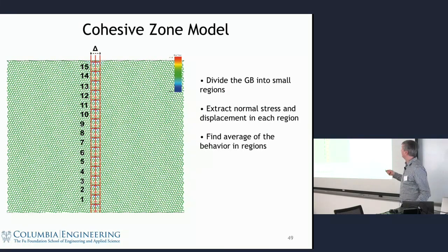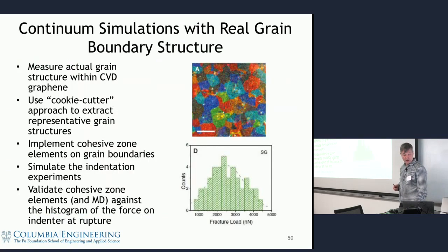And the idea is to build something called a cohesive zone model to look at these grain boundaries and to try to make a substitute for the detailed mechanics with a model of what's going on right at that grain boundary, so we can match the materials or match the properties at the grain boundaries.